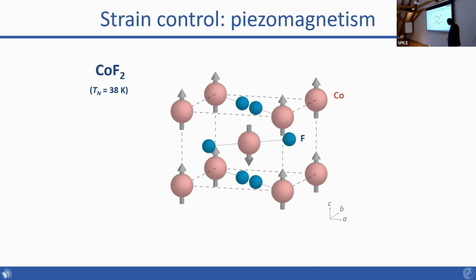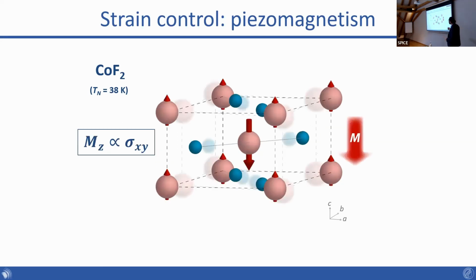But the reason that we are interested in this particular material for demonstrating this kind of phononic control is that it has a very unique property, which is that if you apply a strain to the material along the 110 direction, so in this in-plane diagonal direction, you will actually be able to decompensate the two sublattices. One of the magnetic moments gets bigger, the other one gets smaller, essentially turning this into a kind of ferromagnetic state with a net magnetization, which is going to be linearly proportional to the stress that you apply. Okay, and this is the piezomagnetic effect, which is exactly analogous to the piezoelectric effect, and this is allowed in antiferromagnets of certain symmetries that don't break time reversal, but break combinations of time reversal and some other crystallographic symmetries. And this is one of the simplest piezomagnets that you can imagine.